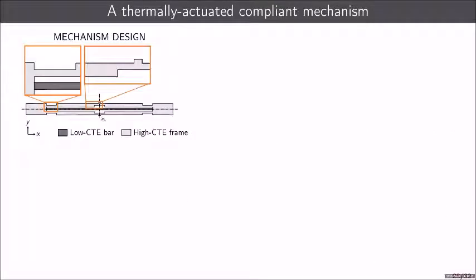So this is our basic unit. What you see over here is basically a mechanism that features two components. One of them, and I also have it in my hand, is a low CTE bar. So there is this dark region at the center. It's a bar with a low coefficient of thermal expansion. In our case, it's made of titanium with a coefficient of thermal expansion of 8.6 or so microstrains per degree Celsius. So this is very small.